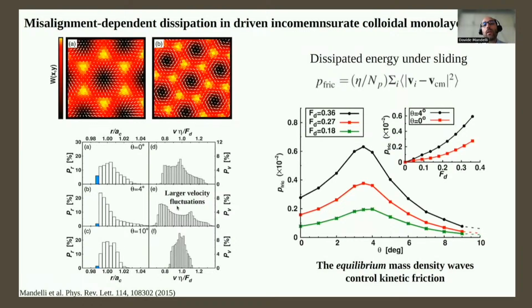Now, the square of the velocity fluctuation is directly proportional to the frictional power dissipated upon sliding, and so this gives rise to a non-monotonic behavior of kinetic friction as a function of the angle theta, as reported here, where kinetic friction reaches a maximum at the optimal angle, where the intensity of these mass density waves is larger. So this suggests that kinetic friction in this regime, in the superlubric regime, is controlled by the equilibrium mass density waves.